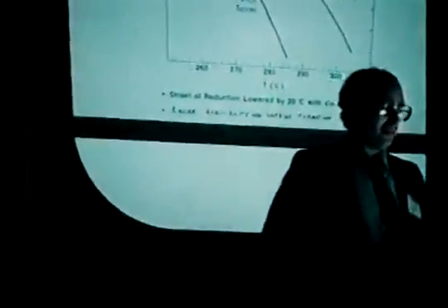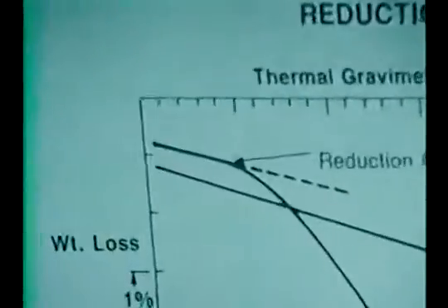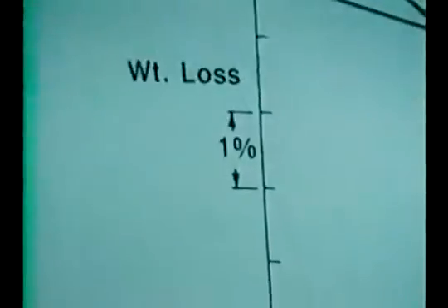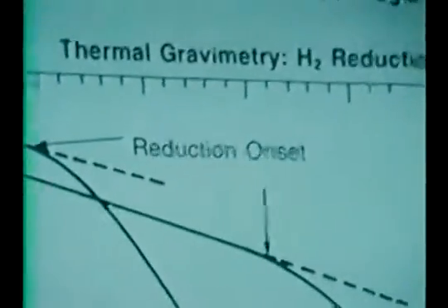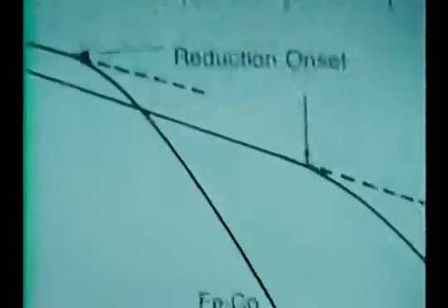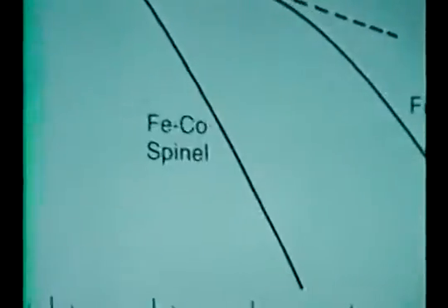Now, are there ways of starting with an oxide and getting to a similar type of carbide, which will give us similar behavior to what we've seen on the laser catalyst? Well, I'm only going to be able today to give you a suggestion of an approach to that. One of the ways of doing that would be to try to influence the degree of reducibility of the catalyst. That is, if we can get the catalyst to be more reducing, that will correlate with its ability to form the carbide at lower temperatures. If we can do that, we can probably make that carbide without any of this extra carbon around it.